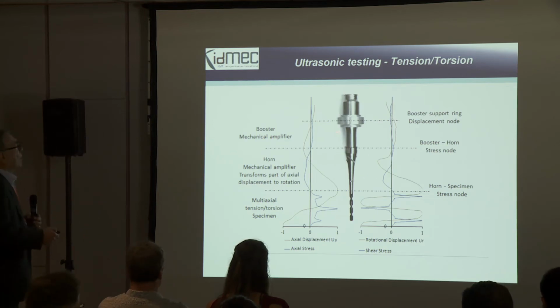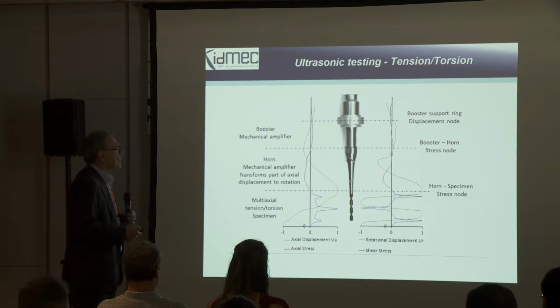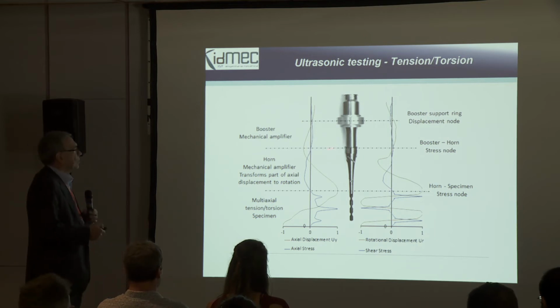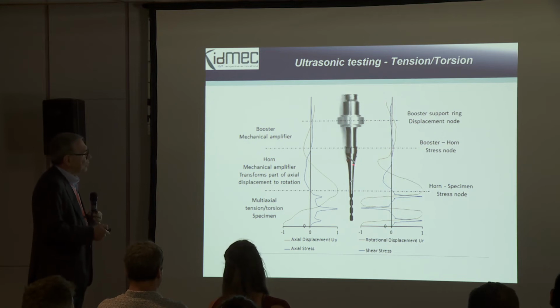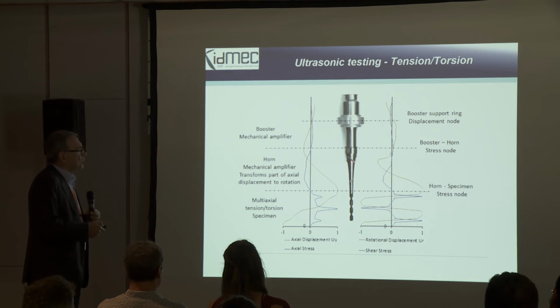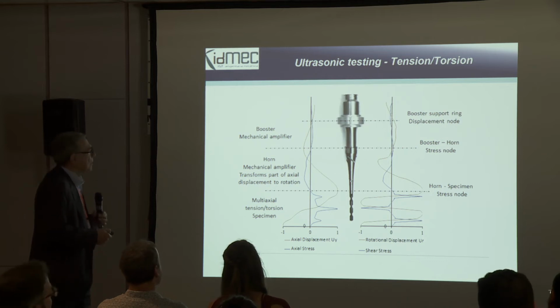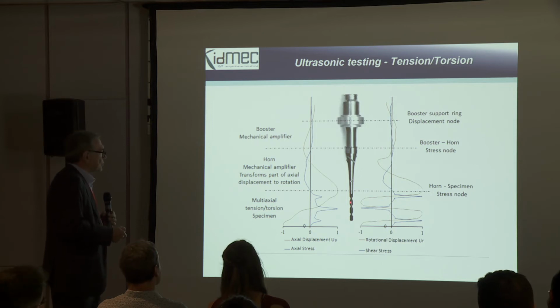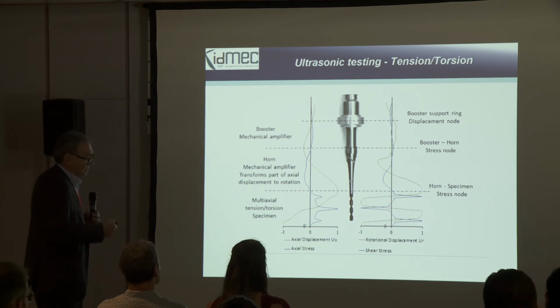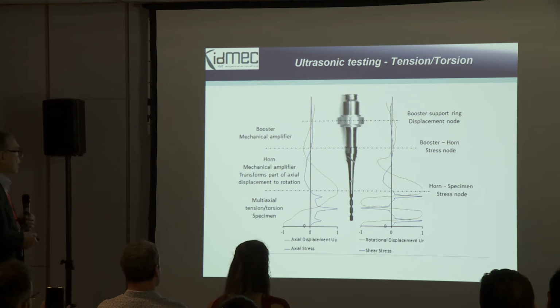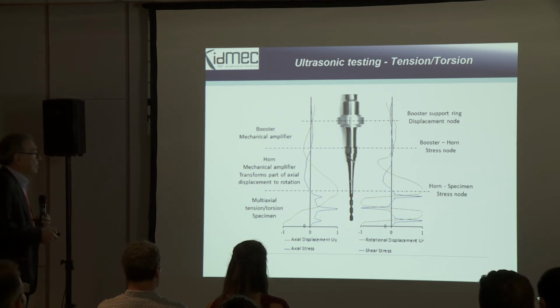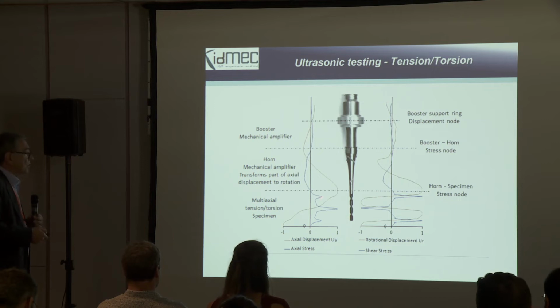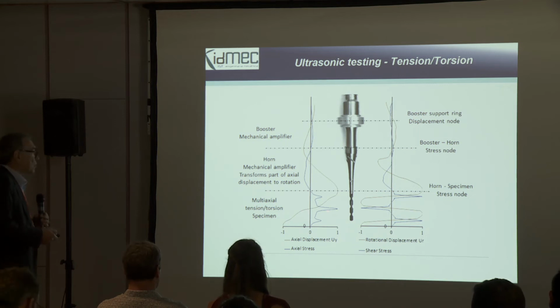So this is the solution that we have. So we have the piezoelectric actuator, we have our horn. So we make grooves over there in order to transform the axial movement into axial and torsion and rotation. And after we have here the solution with the 3 specimens in order to have everything in resonance, either rotation or axial. So as we know, of course, in this throat and this throat, we also have tension and torsion, but the tension is much lower than torsion, so the specimen will break here and not there or there.